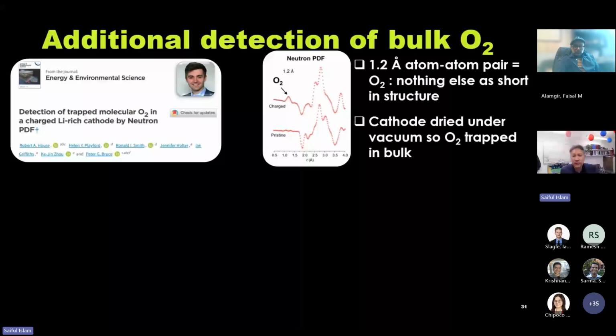What about other techniques? This is work of Rob House using neutron diffraction PDF, pair distribution function analysis. And again, from the plot there, you can see that there are some features in the charged state not seen in the pristine. That 1.2 angstrom atom-atom pair is a signature for molecular O2. Nothing else has that short distance in the structure. This cathode was dried under vacuum, so the O2 is trapped in the bulk.